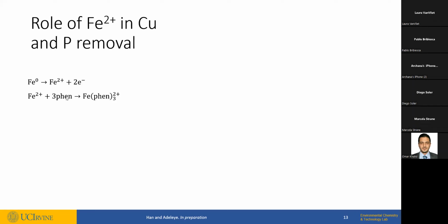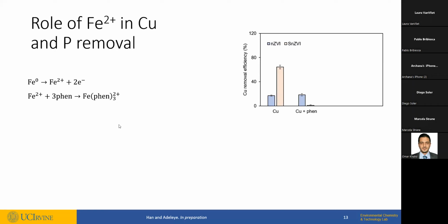So one way to tease that out is to repeat the experiment, but decrease the amount of Fe2+ that is available. And the way we did that is by adding phenanthroline to the reaction. And phenanthroline actually is a complexing agent. It's a ligand, and it's a good ligand for iron. So it pretty much decreases the amount of Fe2+ that is present.